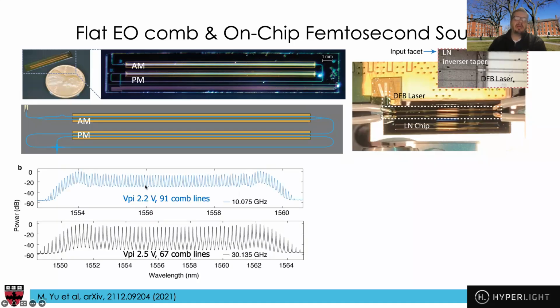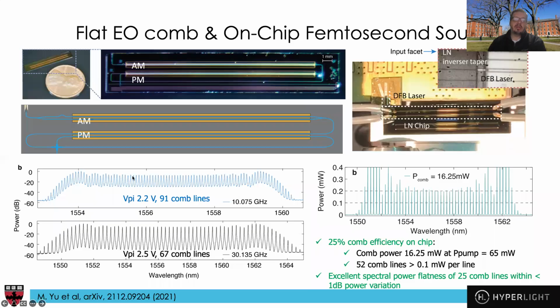And here is experimental data that shows the same device driven at 10 gigahertz and 30 gigahertz. We can get 67 comb lines, and the comb spectrum is very flat. In both cases, V pi is very low. The flatness can also be nicely seen in linear scale, whereas this here is log scale. If you show this comb spectrum in linear scale, you see that these linear comb lines, which are the ones we would use, have a very, very flat spectrum. Total comb power is roughly 25% of the CW pump, which is pretty good conversion efficiency. And also power per comb line is pretty high. So we were quite excited about this.